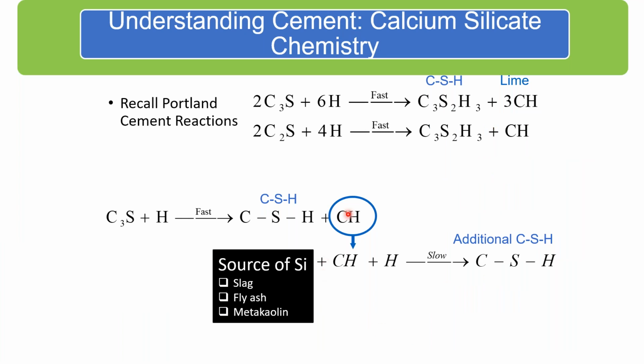Now, the way we typically look at cement is, if I look at the primary ingredients of cement, the tricalcium and the dicalcium silicates, they react with water through a hydration reaction, and what I get is calcium silicate hydrate, and a lot of lime is produced. And initially, it's now probably five or six decades old, we discovered that if I add a source of silica in the form of fly ash and slag, then I can produce additional CSH. So the initial attempts were to add them as additives, and we found that we were getting enhanced strength because the silica was consuming lime and giving us additional CSH.